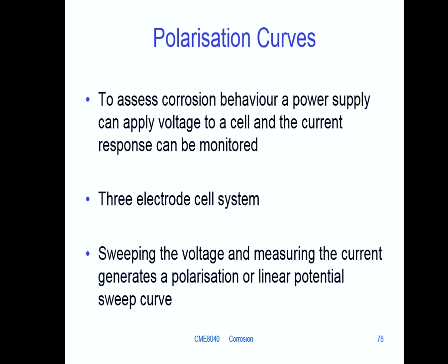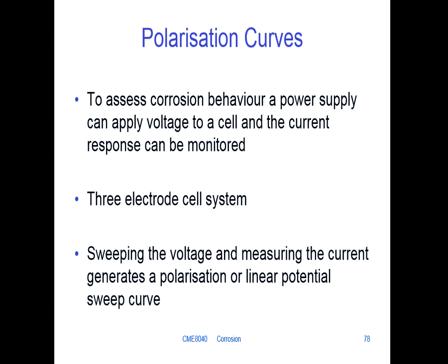For the reference electrode, do they use a hydrogen electrode or a different one? For convenience, you'd probably use something like a saturated calomel electrode or a copper sulfate, or one of those ones that's in the plastic tube that's handy to stick into a cell.